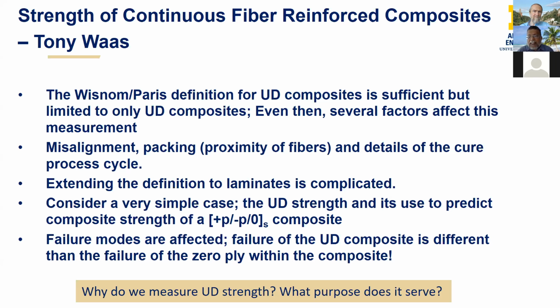First, you can see that, like Ramesh showed, the UD composites fail in a fairly deterministic manner, right? You start failure, it progresses, it splits, and then the fibers break. You can see that with the pictures. But you'll be surprised if you look at how the 0 fibers failed in the plus P, minus P 0 composite. You'll realize it's not the same as when it failed in the UD composite.